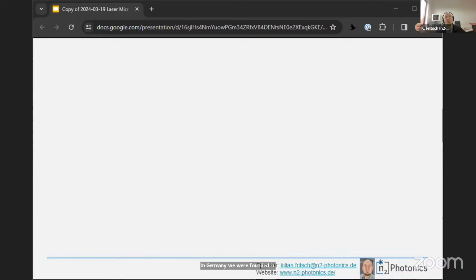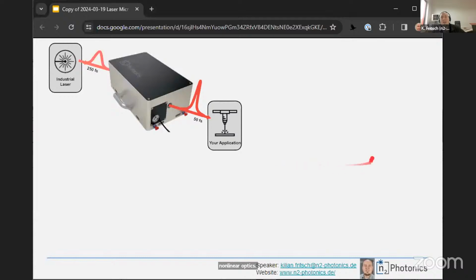We are a small startup company from Hamburg, in Germany, where we were founded in 2022, and the core technology of our business is, as you mentioned, laser pulse shortening or laser pulse compression based on nonlinear optics. For that, we developed a product. Basically, we're starting with a commercial industrial grade laser system that you're already all familiar with in the femtosecond range. And usually when the industry is talking about femtosecond range, we mean hundreds of femtoseconds, so around 250, 300, 400 femtoseconds. That is something that is commercially available from many suppliers. But what we can do now is shorten these pulses by extending the frequency range via self-phase modulation and compressing the pulses in the time domain down to 50 femtoseconds or even shorter, depending on your needs. And this way, optimize your application.